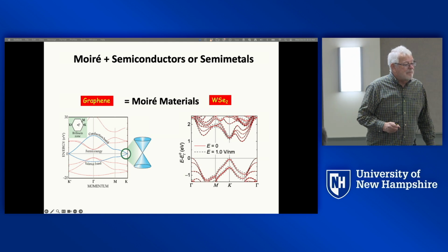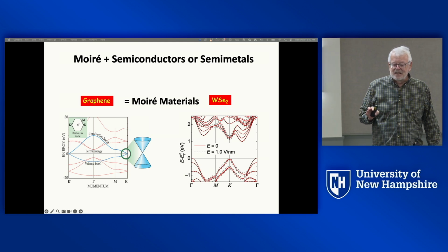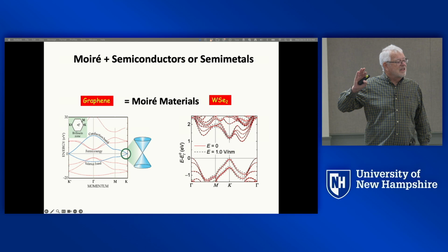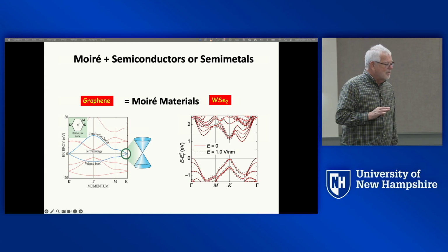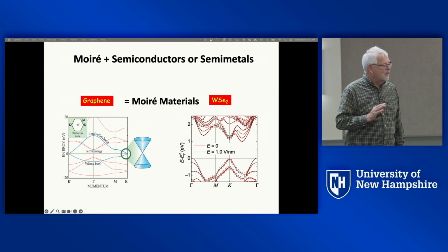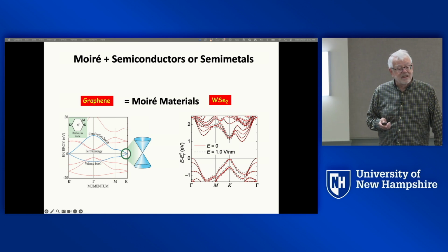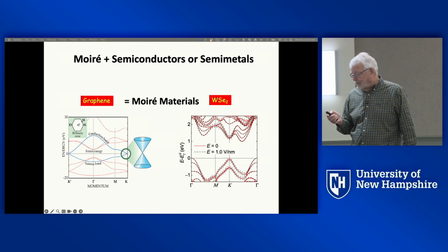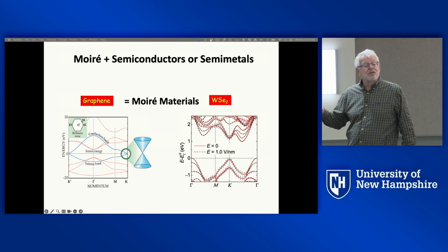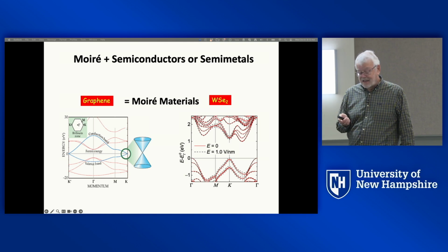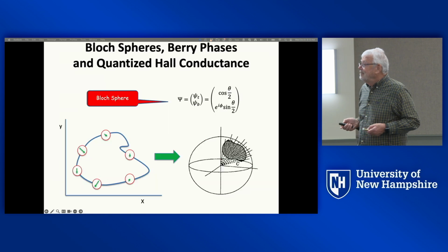Okay, so that's the reason why in these materials it turns out that these Moirés formed from 2-dimensional crystals are actually not crystals. They're not strictly periodic. Only the Moiré pattern is periodic, but over a limited energy range, usually the energy range of interest, the electrons only see the Moiré pattern. Okay, so that's the reason you can make an artificial crystal, and it wouldn't work if you had a 2-dimensional metal, for example, like niobium diselenide.